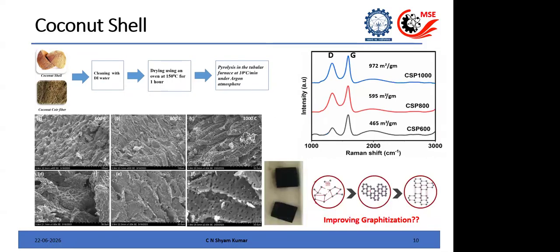Something similar you can also observe with the coconut shell. I'm just giving you some examples. Here also you can clearly see from Raman that you have an increase in the sp2 content as you increase the temperature from 600 to 1000. You can use the D and G band to have an idea about the increase in the graphitic content. And from the SEM images, you can see the porosity is increasing. So again here you have three different microstructures in both samples at 600, 800, and 1000, and the properties will change because of this microstructure and morphology.